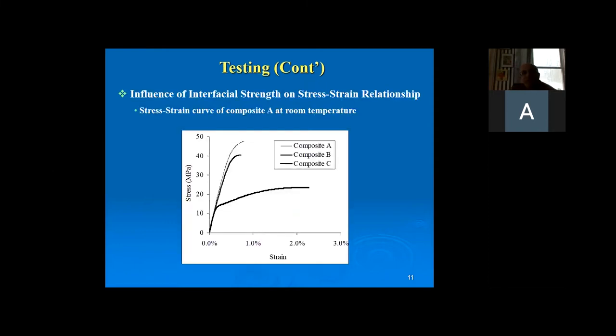Now, when we test these composites A, B, C under uniaxial strain at room temperature, so again, composite A, we have a cohesion promoting agent between the matrix and the filler. So that means that the bond between the filler and the matrix is very strong. We are using something like a glue to improve the adhesion between the matrix and the filler. It gives us the highest ultimate stress, almost 50 megapascal, but however, it is very, very brittle because the fillers are ceramic, and ceramic is a very brittle material. It governs the stress-strain response of the material.